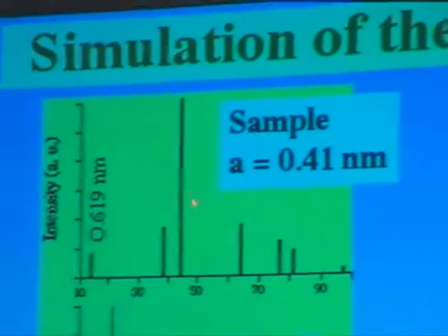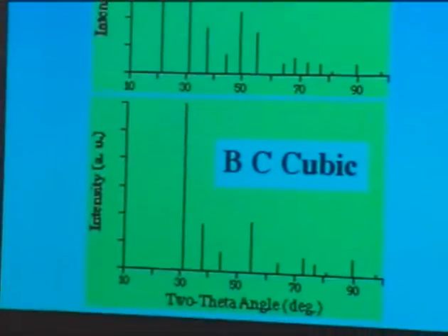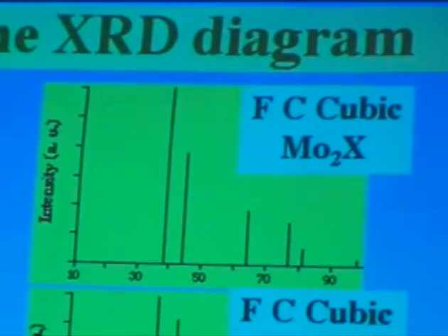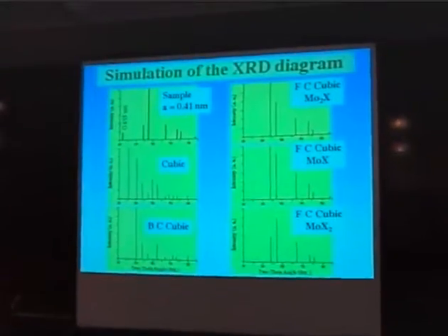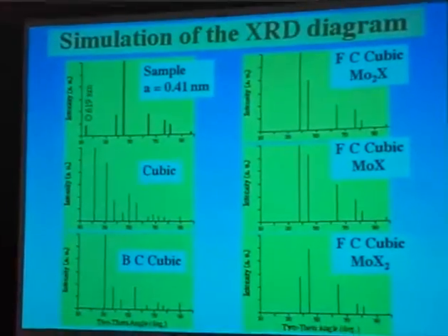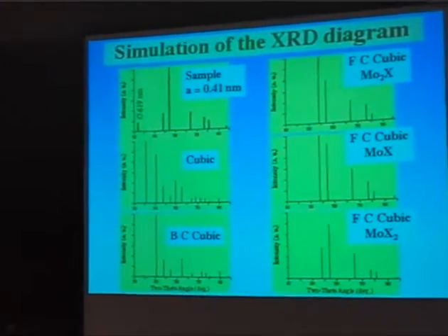So that is a sample diffraction. What we have, as you see, is 5 rays here and 1 here. This one we shall talk about later. So we knew that we have a cubic sample, because when we were looking in the transmission electron microscope, whatever the orientation was, we always had these 0.41 nanometer distances. So we decided to fix these distances and then start to make modelization.